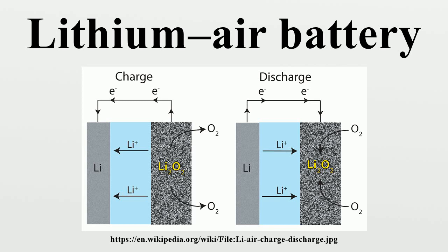Challenges. As of 2013, many challenges confronted designers of Li-air batteries. Cathode. Most of the current limitations in Li-air battery development are at the cathode, which is also the source of its potential advantages. Incomplete discharge due to blockage of the porous carbon cathode with discharge products such as lithium peroxide is the most serious. The effect of pore size and pore size distribution remains poorly understood. Catalysts have shown promise in creating preferential nucleation of Li2O2 over Li2O, which is irreversible with respect to lithium. Atmospheric oxygen must be present at the cathode, but contaminants such as water vapor can damage it.